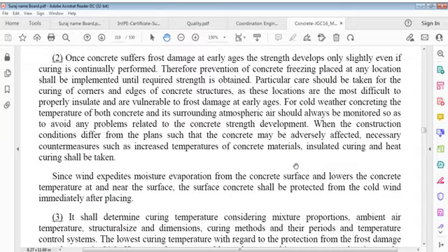Once concrete suffers frost damage at early ages, strength develops only slightly, even if curing is continually performed. Therefore, prevention of concrete freezing placed at any location should be implemented until required strength is obtained. Particular care shall be taken for curing of corners and edges of concrete structures, as these locations are most difficult to properly insulate and are vulnerable to frost damage at early ages.